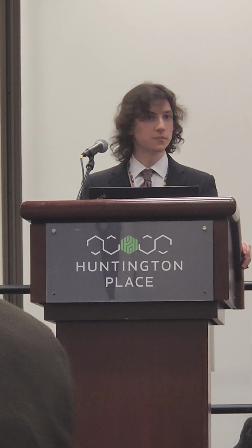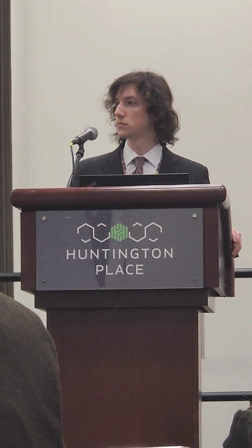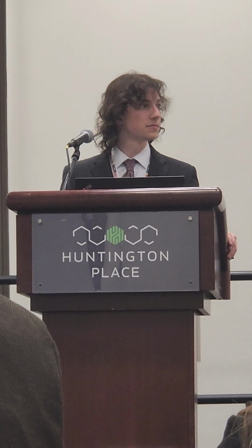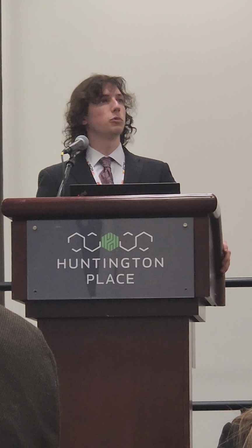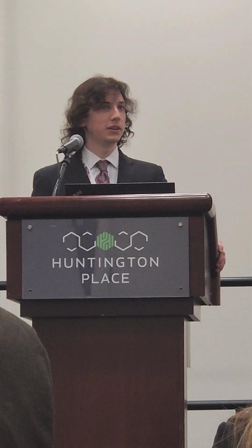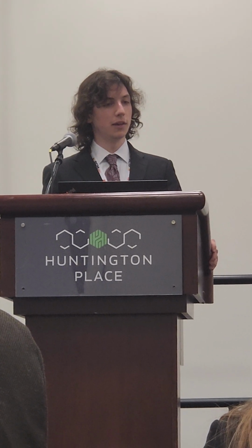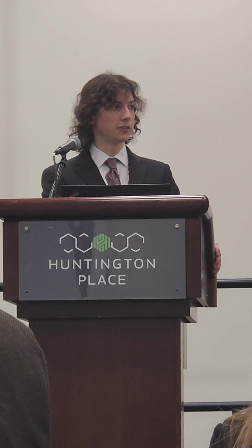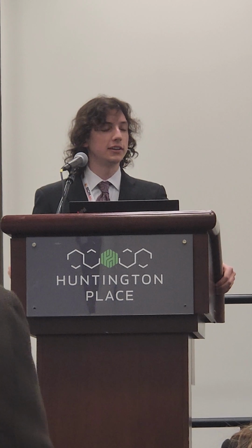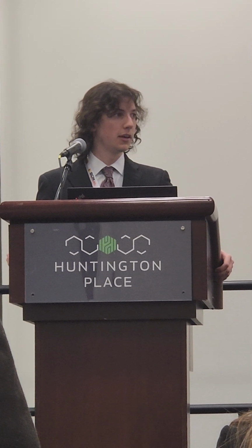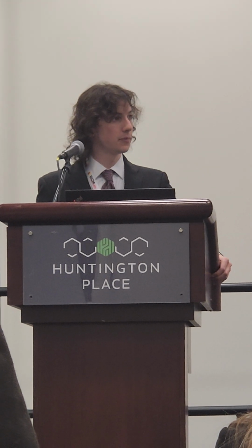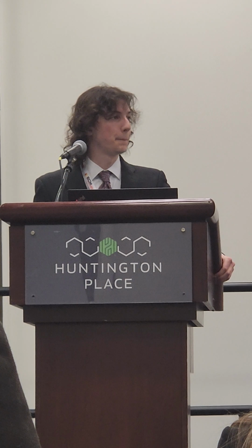Any questions? I have a question. So it was a simulation of carburization? We refer to it as simulated carburization because it simulates the heat treatment without a carburizing atmosphere. So it's placed in a furnace at room temperature, heated 8 C per minute, and then left for whatever amount of time after you hit temperature. So not literally simulated. What's the atmosphere that the parts are under? Just air. Yeah.